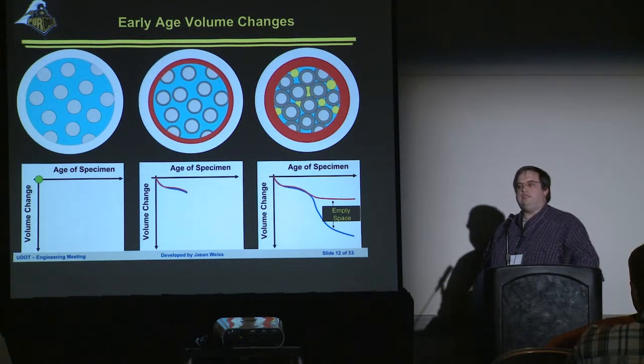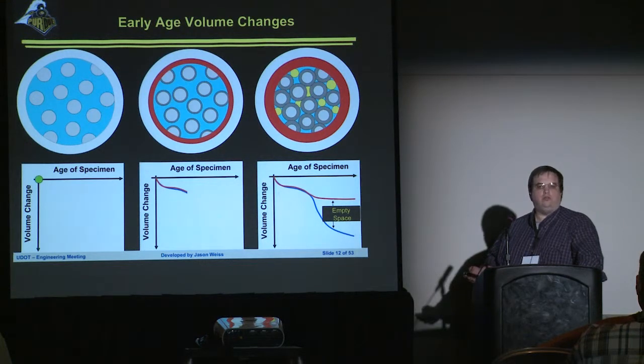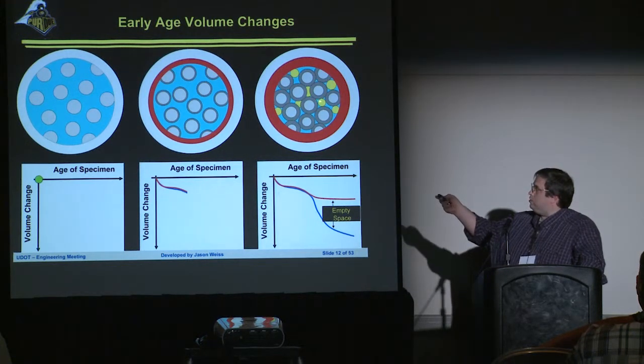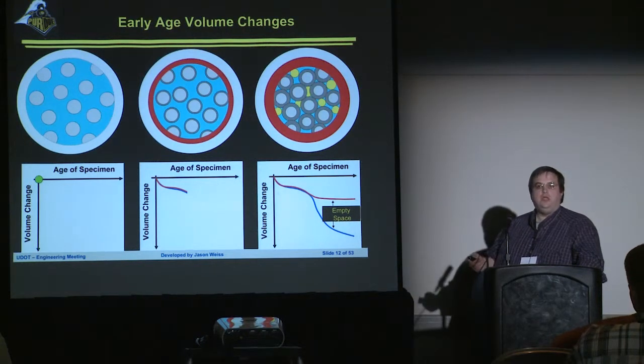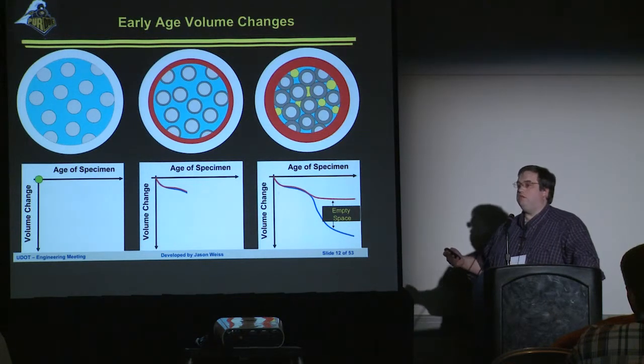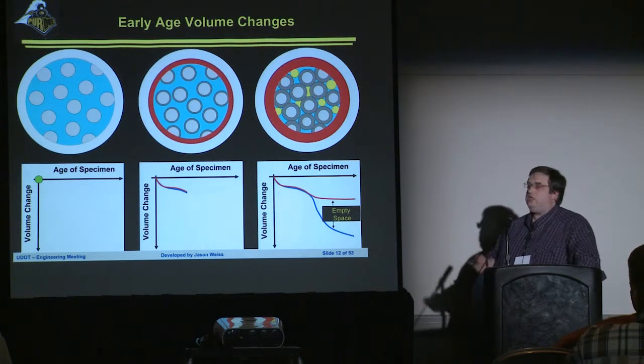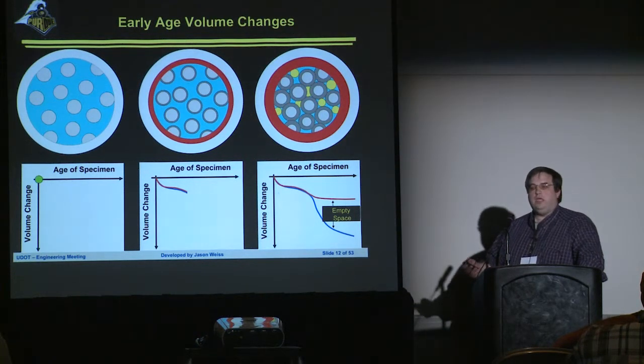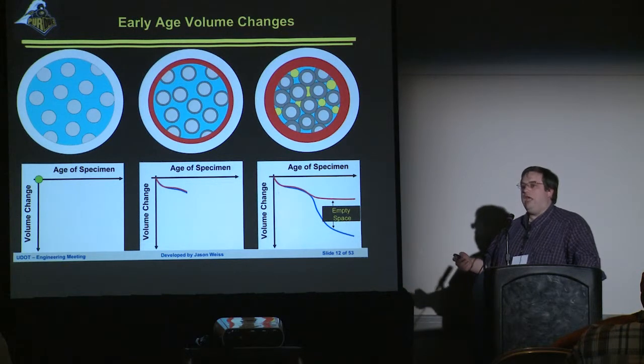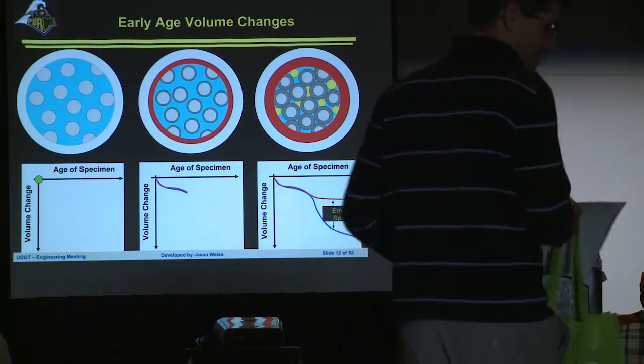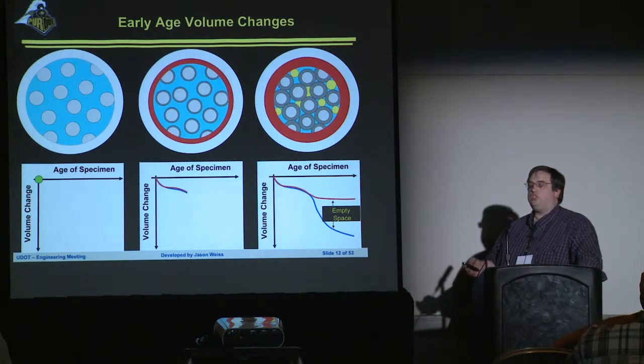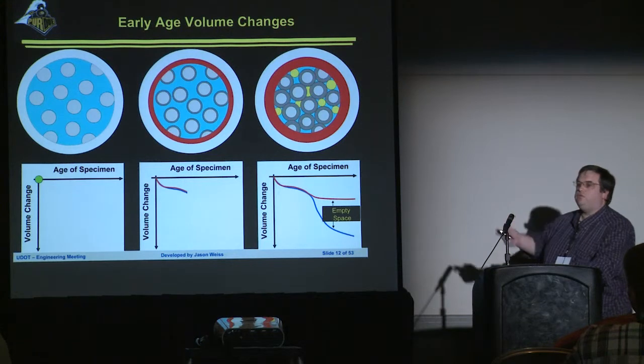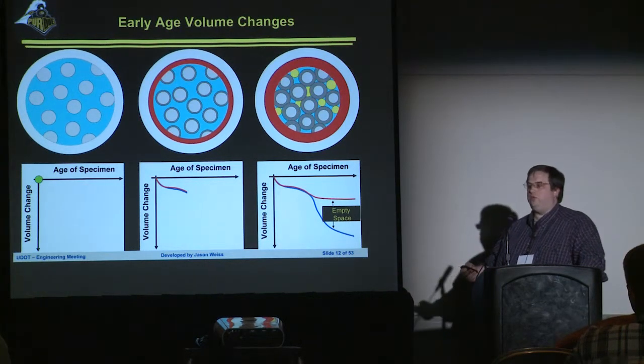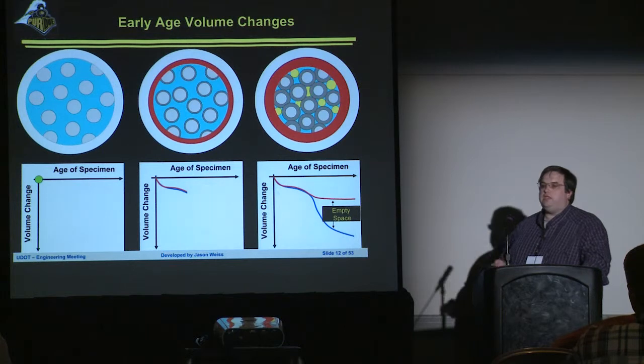So what has to happen in these systems? Vapor-filled spaces need to start to form inside of our system. So these pockets start to open up, these vapor-filled pockets. These pockets are going to give rise to that thing we called self-desiccation. When we first started looking at this, we said we should be able to hear these pockets forming. It turns out that we can use a technique called acoustic emission, and we can actually hear when these pockets start to form. They start to form right after setting. So really the issue is, these vapor-filled spaces are going to give rise to stresses developing in the fluid, they're going to give rise to shrinkage, and they're going to behave exactly the same way as if these vapor-filled spaces were created by water being lost to the environment due to drying.